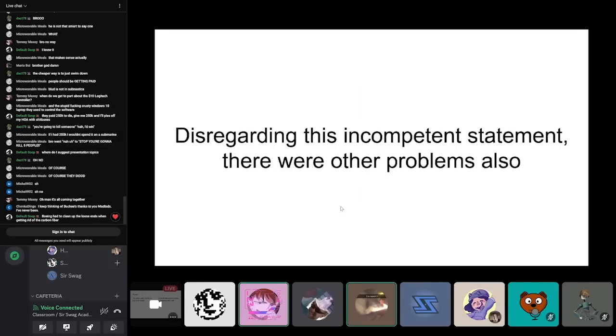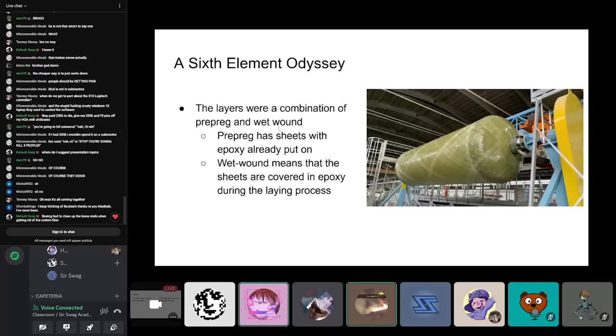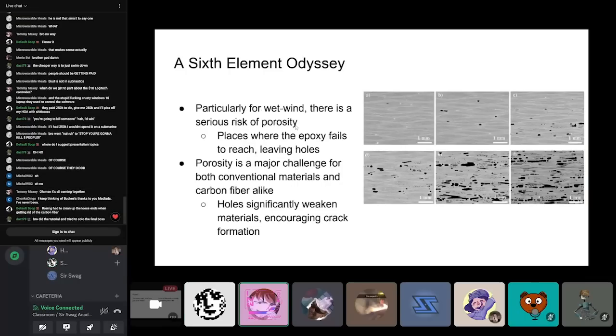Now, disregarding the incompetence in the design, there were other problems also. Because it was half pre-preg and half wet wound, there were problems actually making it. There's a really big issue of something called porosity. That's where you get holes in your carbon fiber, places where the epoxy doesn't reach and you get holes left behind, and this causes serious issues. Holes significantly weaken materials and they encourage cracks to form.